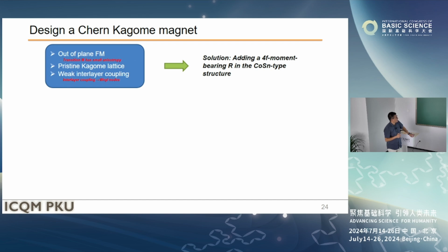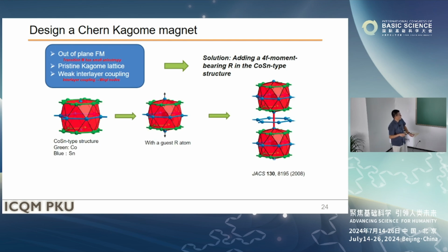So what should we do? We found a particular structure which can be seen as adding local-moment-bearing rare earths inside this well-known CoSn-type structure. In the CoSn structure, you can see the cobalt atoms form a Kagome lattice, and the tin atoms are like this. And if you put the rare earths inside this space, the pressure just pushes the tin atoms up and down, and then you are left with a pristine Kagome lattice formed by the transition metal. And because this site is bigger, in the next layer you cannot put another rare earth inside. So you put it in the layer after, which makes your space bigger, right? So your interlayer coupling is expected to be weaker, right?